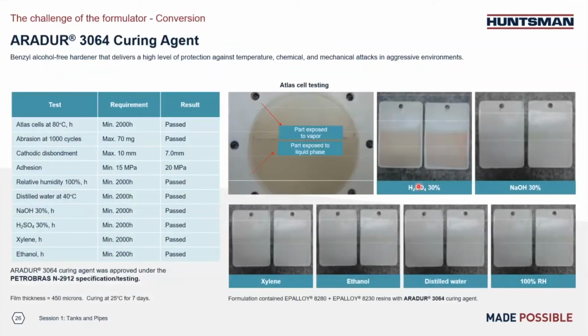So here is more data on this ARADUR® 3064 curing agent. You can see it is a benzyl alcohol-free hardener, has overall pretty good temperature, chemical, and mechanical properties. It is approved under the Petrobras 2912 specification test. And if we look at the table on the left side, you can see it has very good overall testing results. For example, we can pass the Atlas cell testing at 80 degrees C for 2,000 hours. If we look at the picture on this side, you can see both the vapor phase and the liquid phase, the panel is still looking good after 2,000 hours.